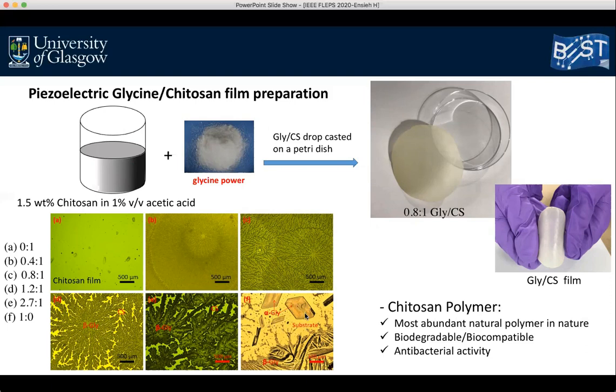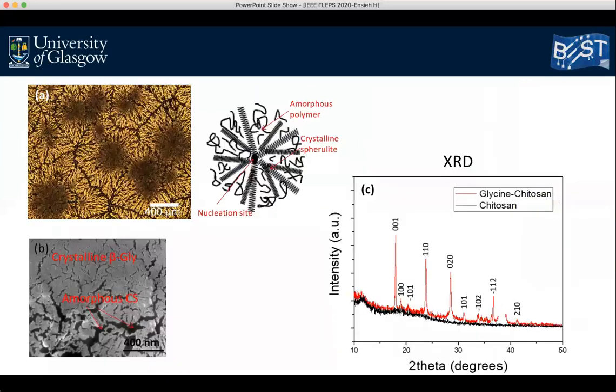So for all the other measurements, we focused on the film that was obtained from 0.8 to 1 of glycine to chitosan. This is because it was a very uniform film, had a uniform spherulite structure in the entire film, and the film was very flexible and had significant piezoelectric properties. In terms of the mechanism of the growth of crystal, chitosan is used as the matrix material, and the grown crystals are embedded in the chitosan film.